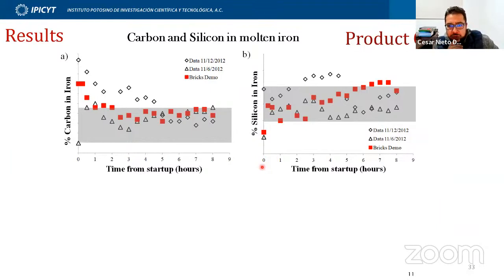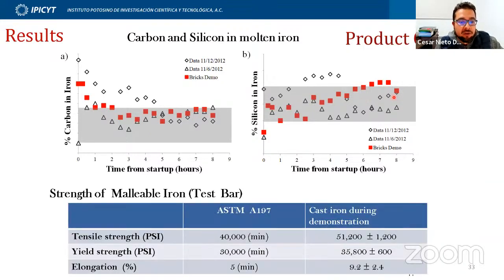Here is just some data about the metal quality. The carbon and the silicon in the iron are shaded in this gray rectangle, and you can see that the red squares, which are the data from the anthracite briquettes demonstration, are very similar to the days when they were using 100% coke. Also, the strength of the iron that was made those days was within the specification according to the producers.